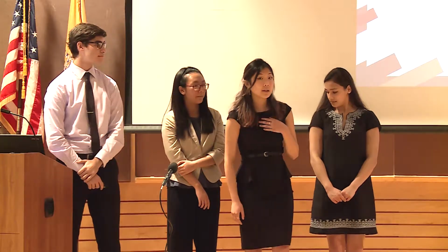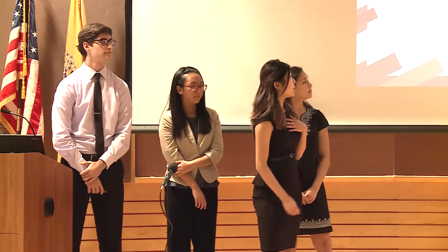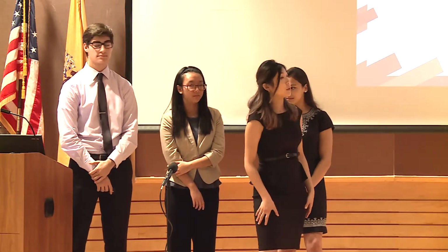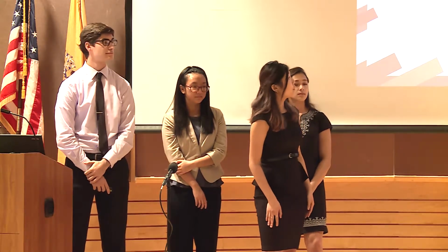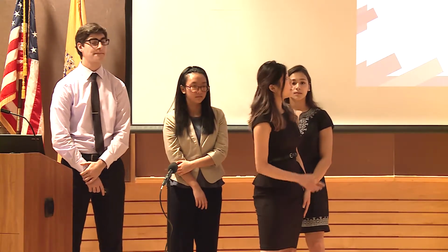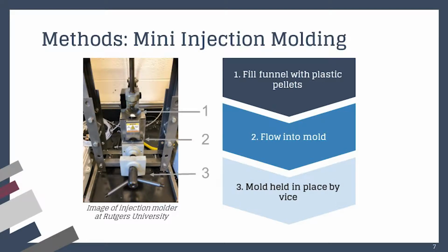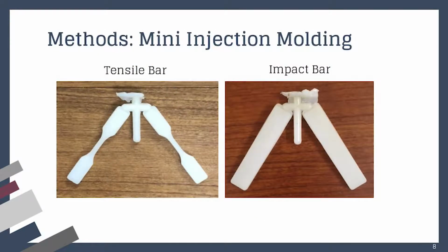So once we have these pellets, in order to make the bars that we'll be testing, we use an injection molder. So we put the pellets into the funnel and waited for it to melt into the mold, which is held there by a vise. And so here are 2 examples of successful bars that we made. You can tell that they're successful because the plastic reached the bottom of the molds, creating perfectly clean-cut corners.